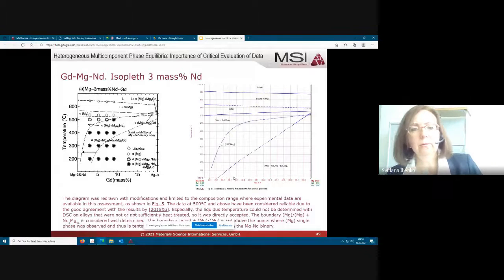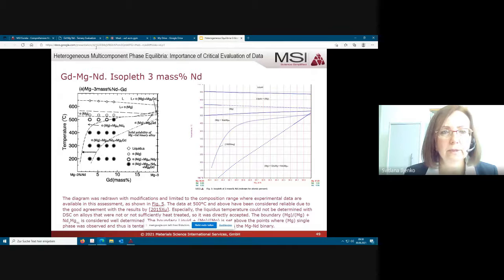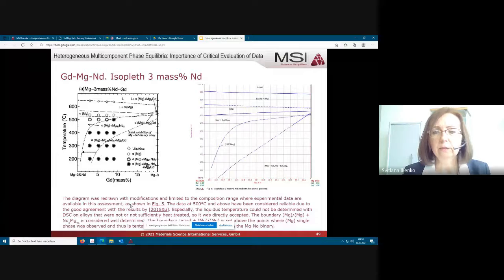Yeah, there is also an isopleth section, a vertical section at 3 mass% of neodymium. So this is the section as it is presented in this document, in our critical evaluation, and this is the original article on which this phase diagram is based. So first of all, our authors accepted only the range which was experimentally confirmed, and this is where we more or less see the experimental points. All others were considered as speculation, and therefore were not reproduced here because that would be too speculated. Also, this text describes in detail at which temperatures, for example, the data at 500 degrees and above have been considered reliable due to the good agreement between different other publications also.